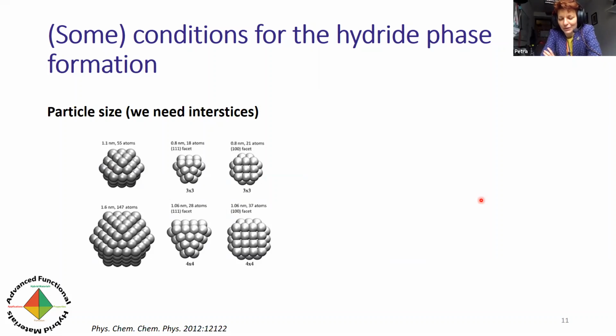And so one more thing that we need to consider, and this is very simplistic in a way, but I just want to capture the essence of what else needs to be considered when we want to look at it. And of course, there are some conditions that need to be fulfilled in order to control whether or not the hydride phase or this interstitial hydride phase in palladium may form. And one of these is the particle size. So we have seen that for the interstitial hydride, obviously you need interstices for the hydrogen atoms to be taken up. So if we don't have a bulk of palladium, we won't have a hydride phase either.